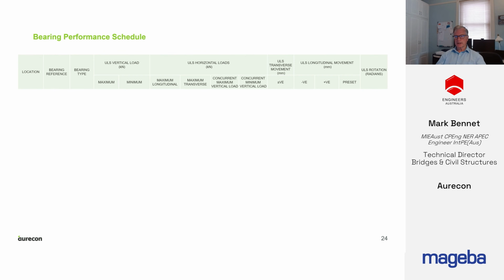Bearings or bearing load sets where friction can be accounted for in the calculation of anchorage capacity of the bearing should be indicated. The required cube strength of mortar pads and the maximum pressure on the reduced effective area at the interface of the attachment plate and mortar pad should be shown on the bearing drawings. A maximum value of 55 MPa is recommended. For bearings with an advanced sliding surface, the maximum operating temperature of the bearing should be shown on the bearing drawings. As a guide, the maximum air temperature plus 4 degrees is recommended.